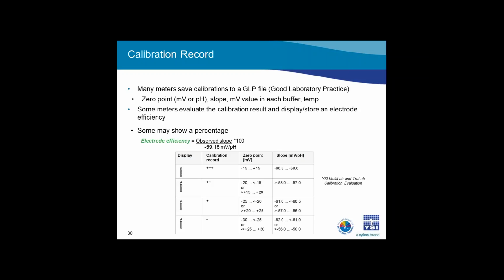Typically, the information stored in a GLP record includes the number of calibration points, the buffer values used during calibration, and the millivolt value from the sensor at each calibration point. Some meters will calculate the slope and electrode efficiency for you as well. The electrode efficiency is the actual slope divided by the theoretical slope from the Nernst equation, and then multiplied by 100 to give you a percent value.